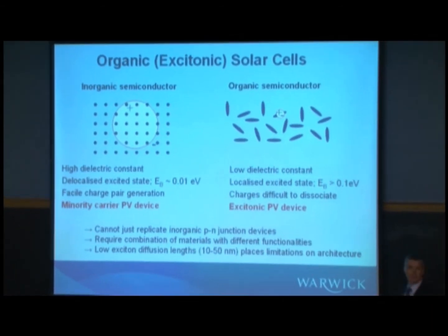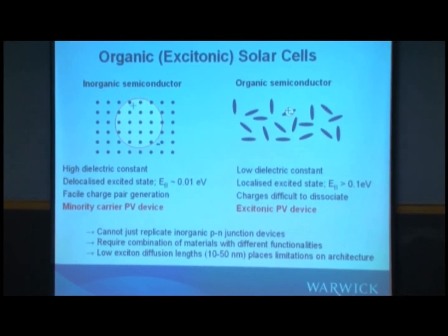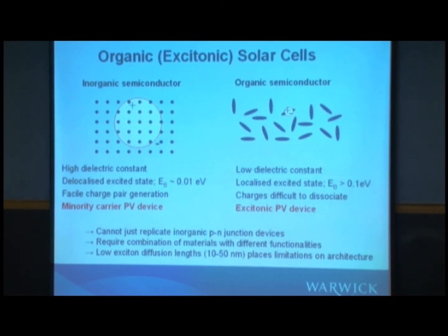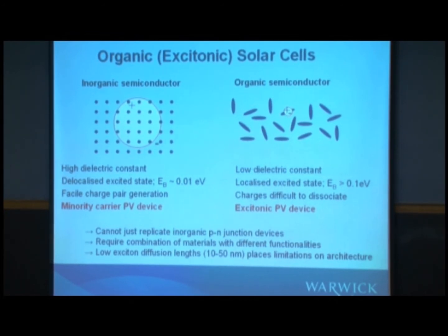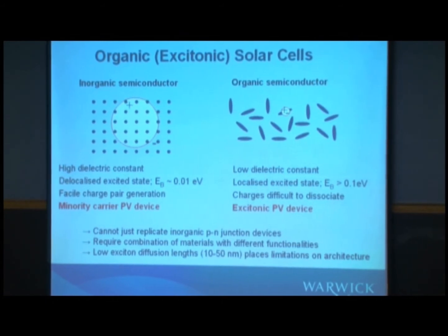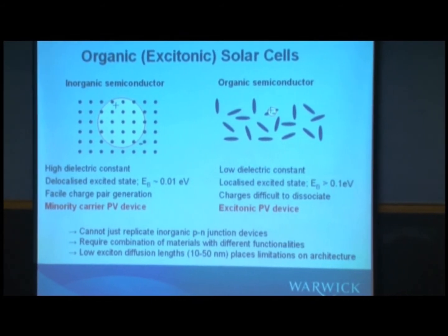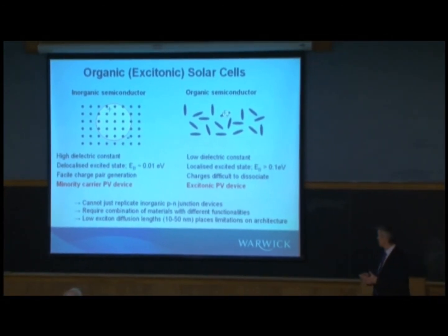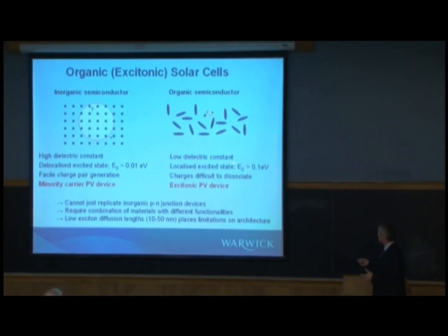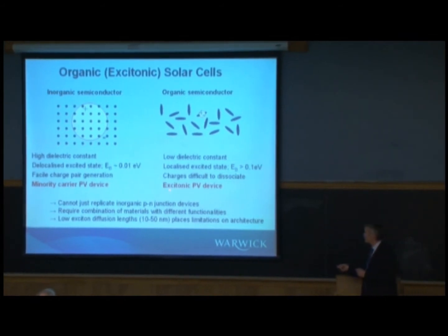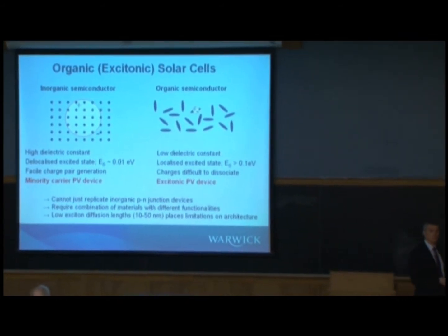Now, in an organic semiconductor based on molecules or dyes or polymers, then you have a quite different set of physical characteristics. You have a low dielectric constant, a highly localized excited state with a high binding energy, certainly above 0.1 electron volts, probably around 0.3 electron volts. So dissociation into the free charges, and I'll come back to this in a moment, is actually very difficult and is one of the challenges in building your device. Because that dissociation is such an important step, we call it an excitonic solar cell device.